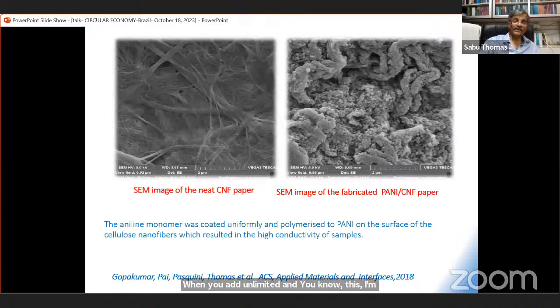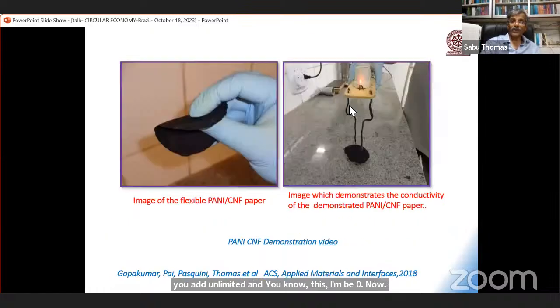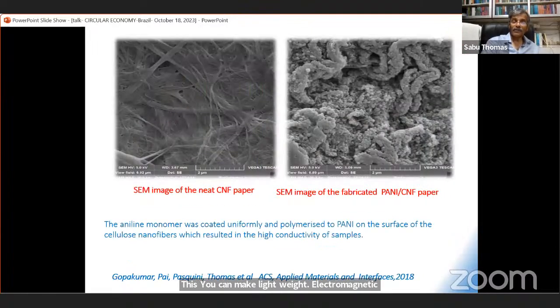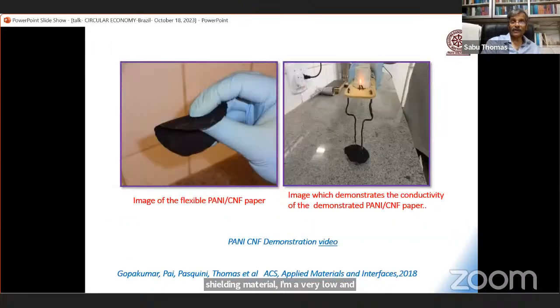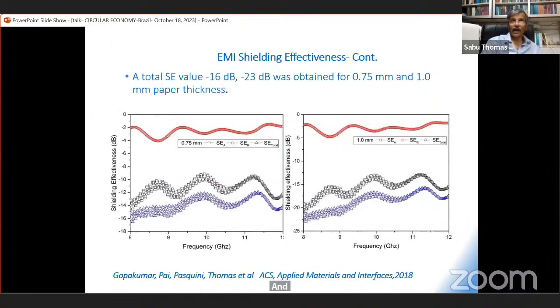Now, this is the SEM of the nanocellulose paper, and this is the SEM of the PANI-CNF fiber. And you can see that this is an extremely conductive material, and it is also lightweight. You can make lightweight electromagnetic shielding material using nanocellulose and PANI. And the manufacturing is quite a simple process. This could be a very nice material for EMI shielding applications.